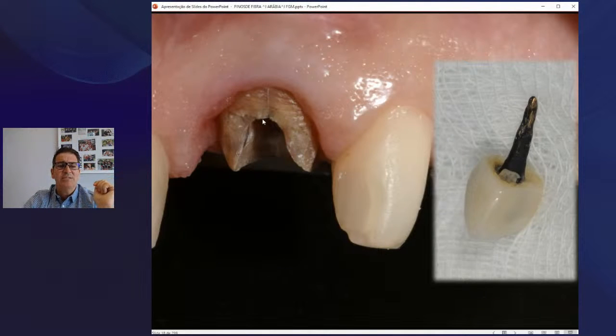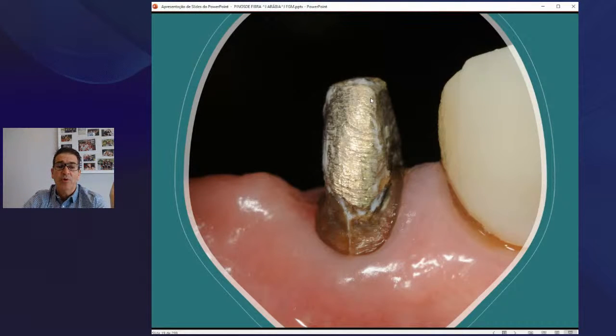So in situations like this, those cracks are very common. And of course, those cracks transform themselves into what? Into fractures. So when we have a crown loosening like in this case, it's because certainly those cracks are opening, and unfortunately there is nothing we can do unless we just take it out and place an implant. So those cast metals, even with the ferrule effect, sometimes they transfer a lot of stress and cause this kind of crack. And those cracks open, and we know what else is going to happen.